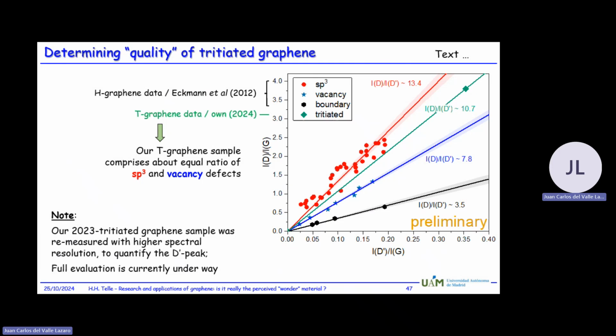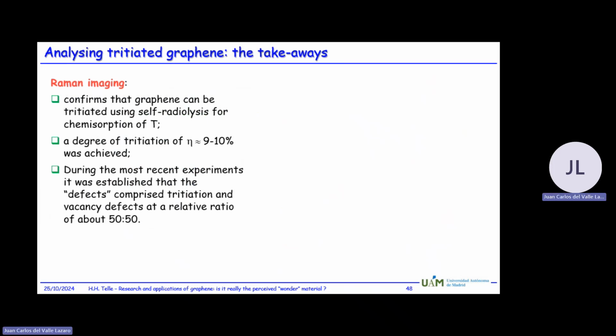So basically, we have seen in our tritium sample that we have a combination of adsorption damage and actual mechanical damage to the system. And this is no wonder, because tritium is radioactive, produces electrons of 16 kiloelectron volts, and they will hammer your material and destroy it along the way. Nevertheless, you can take away from this study that we were able to tritiate the samples for whatever reason, but that we also were able to distinguish between different types of defects, whether it was adsorption or chemisorption, and whether it was actually physical damage to the part.